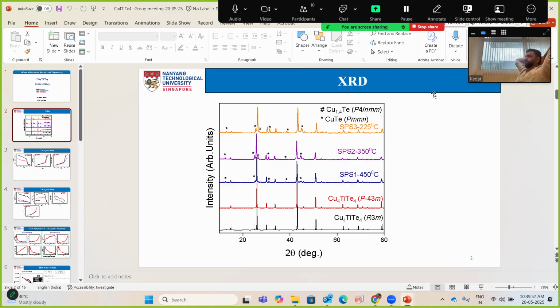Jayanta, the one idea is to go to high temperatures, but the main problem is that you don't expect your phase to be stable at 450, but it is in the SPS, correct? And secondly, it's fully dense. The density is really good.